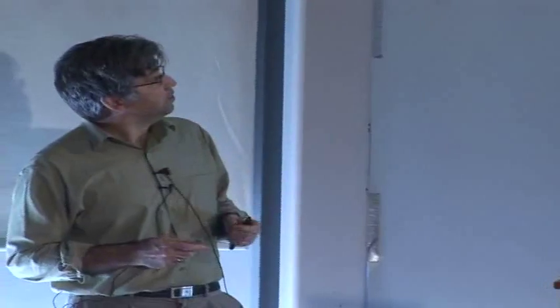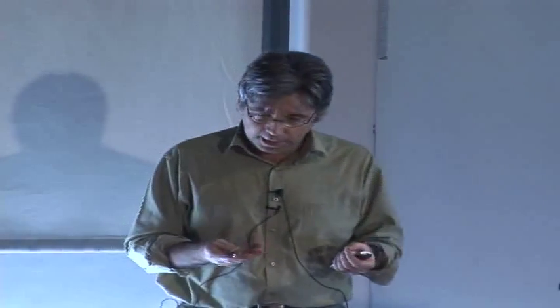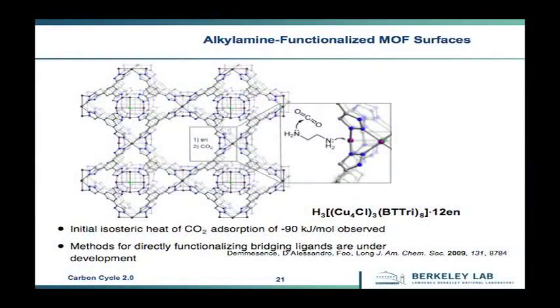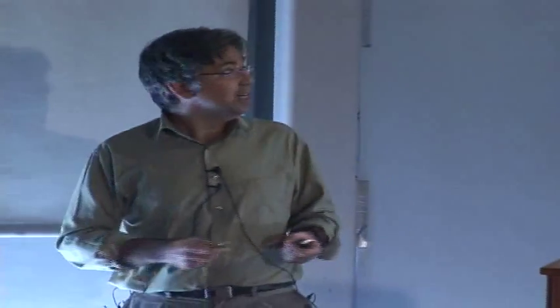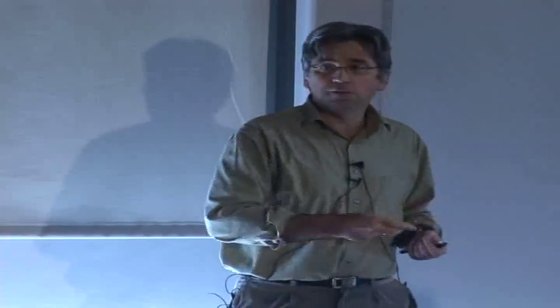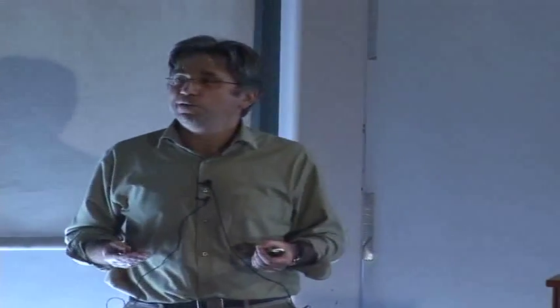What Jeff Long is doing is actually this. He looked at the amine solution and said, well, those amines capture the CO2 actually extremely well, but I don't want to have the water. So can I now develop the chemistry to actually attach those amine groups at the metal sites of those metal organic frameworks? So you have this enormously large surface covered with amine groups in such a way that you can capture the CO2, but now you have this metal framework and not the water which you need to recycle. Well, developing the chemistry to actually cover the interior of such a material with those amine groups is something that has never been done before, and this is the type of thing we're trying to develop with this EFRC.